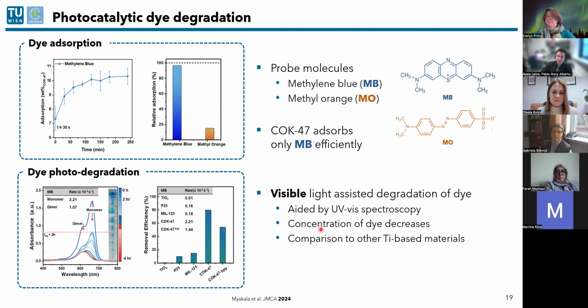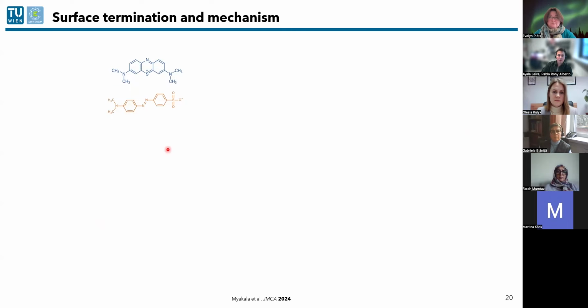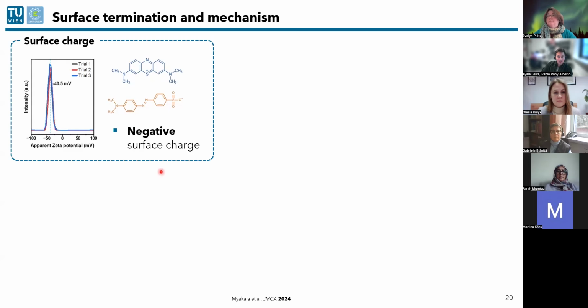We compared COK-47 to other titanium-based materials and saw that it was quite efficient in removing this dye from the water. However, we were still a bit puzzled about the methyl orange dye and why this one didn't get absorbed. If you see both molecules, you will very quickly recognize that not only their structure is different, but their charge is different. This one is positively and this one is negatively charged. We did some zeta potential measurements and found out that our MOF particles have a negative surface charge. So it becomes quite obvious that if they are negatively surface charged, they will attract a positively charged dye, a cationic dye. And this was the key.